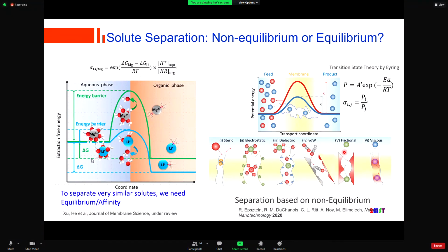To summarize the core information in my talk: I showed you the theoretical philosophy for separation of similar ions. This part I took from a review article from Yale University, from Professor Elimelech, purely based on ion diffusion and some interaction of the polymer membrane with ion size and pore size - like a competition of the rabbit and tortoise. But my philosophy is that for very similar ion pairs, it's better to use equilibrium separation instead of diffusion controlled separation processes.